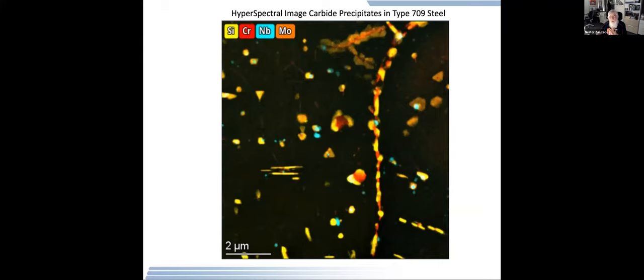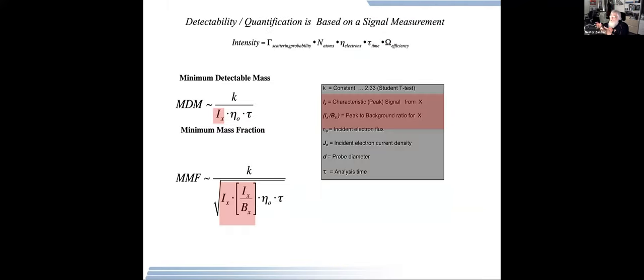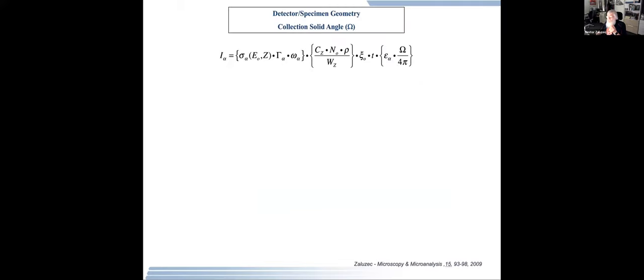So how do we maximize the information we can get from this? That's been part of the work I've been doing over the years. One of which is how do we maximize our detectability and maximize the quantification capabilities of any measurement. And whether you're looking at an image or spectroscopy, we're basically looking at an intensity. And that intensity is dominated by the scattering probability that causes it, the number of atoms that are involved in the interaction, how many electrons we put in, how much time we put in there, and what's the efficiency of the process by which we're measuring that intensity. And that holds whether we're looking at an electron image, electron diffraction pattern, or any spectroscopy. That's a generic formula.